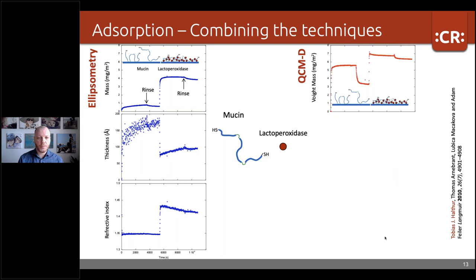Using QCM-D, or using some modeling that is included in the software for the program, you can calculate the wet mass, so that's sort of the total mass adsorbed in your film. And if you then compare the mass obtained from QCM with the one obtained from ellipsometry, you can actually sort of calculate the water content in your layer. And here it's approximately 90% water in this first